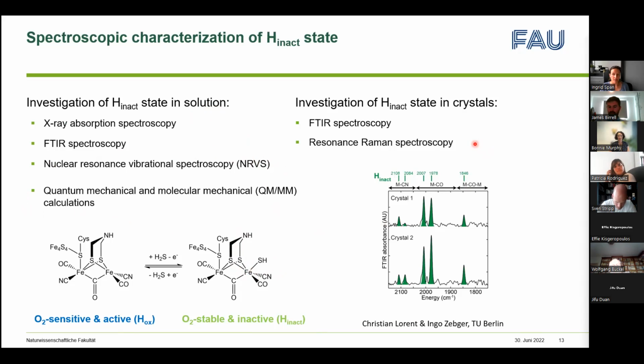And we also performed spectroscopy on the crystals. So usually this is always a problem that we have data on protein in solution, and then we have a crystal structure, and we're not entirely sure what state our crystal structure is in. We know the state of the protein when we set up the crystals, but 3 days later, we don't have a good method of determining that. And with the development of single crystal spectroscopy, we actually have the tools on hand to determine the state of the enzymes in the crystal. And this is work done with Christian Lorent and Ingo Zebger at TU Berlin, Technische Universität. And he was able to characterize the crystals that we sent as the Hinact state.